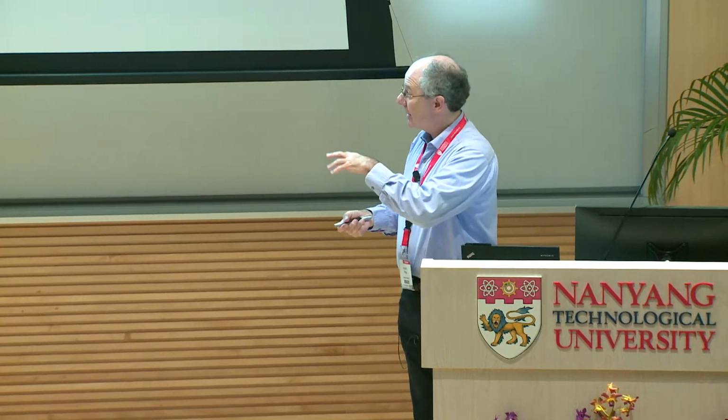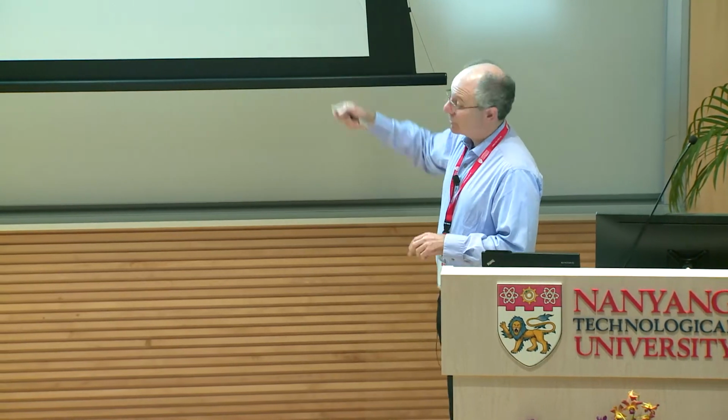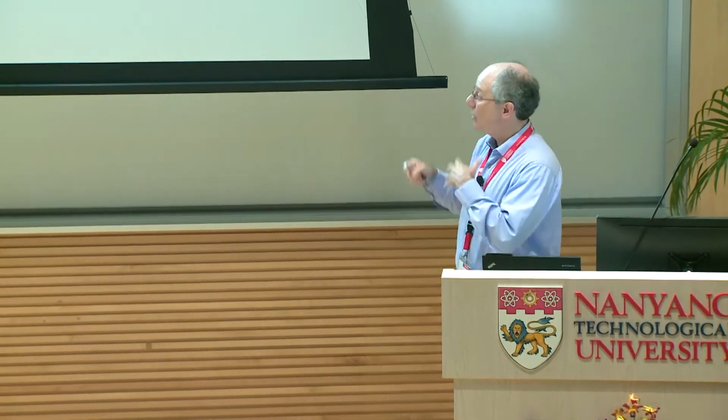Okay. When we're in the gap, when we put in this uniform magnetization and now try to put in the twist, we do get a spin stiffness that's non-zero. It's a little bit of hard work, but you can figure out these coefficients, and this is the result. You can get them quite explicitly. And you can check that these coefficients are such that if you put in a twist, you always raise the energy. So again, it's ferromagnetic.